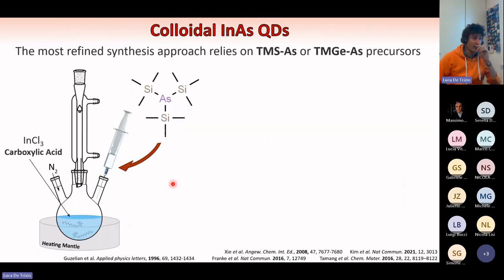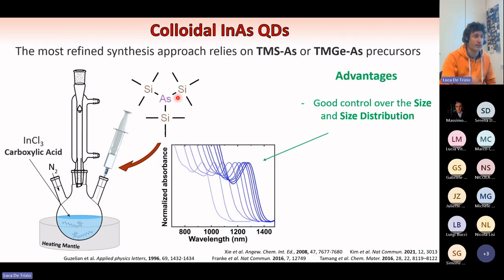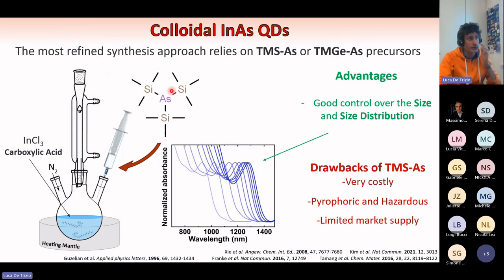As regards the synthesis, the first approach reported in the 90s is based on this molecule, trimethylsilyl-arsine. After more than 20 years now, the synthesis of indium arsenide with this precursor is quite well developed, though still not completely. But the problem is that this precursor is very expensive, is pyrophoric, so it's very hard to handle, and it's not easy to purchase either. So indium arsenide dots made with this compound maybe are not the best option to go to the consumer market.